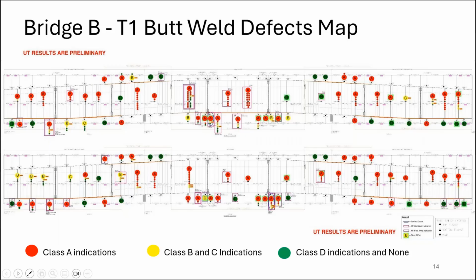We use this, it's a roll plot of the two elevations of the two girders. So the flanges are on top here. This is showing you mostly the webs with all the stiffeners. Every day, we basically track the progress of the UT. And one of the reasons this took so long is you can really see on Bridge B, we were finding that most of the welds had some kind of indication within the T1 steel.